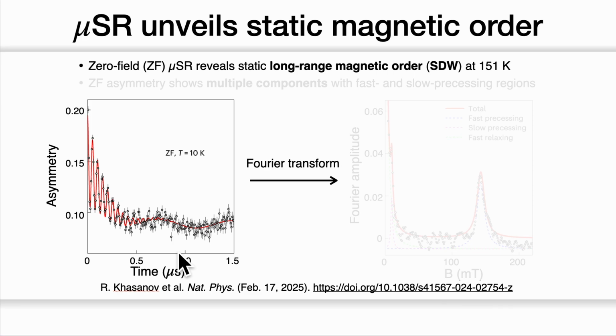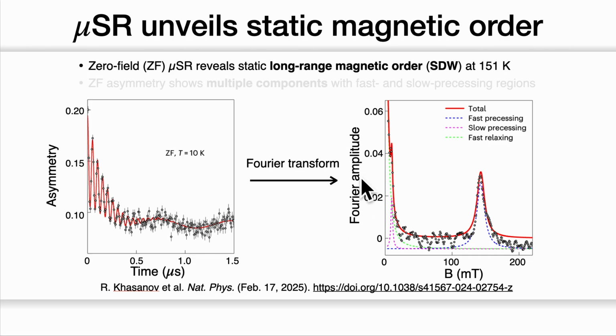We can also perform Fourier transformation on this data to understand what magnetic moments are inside. Here shows the Fourier amplitude as a function of magnetic field. The red curve is the total curve, and we can use fitting techniques to identify fast precessing and slow precessing components. To understand the microscopic magnetic order in these materials from this data, we then rely on first principle calculations.